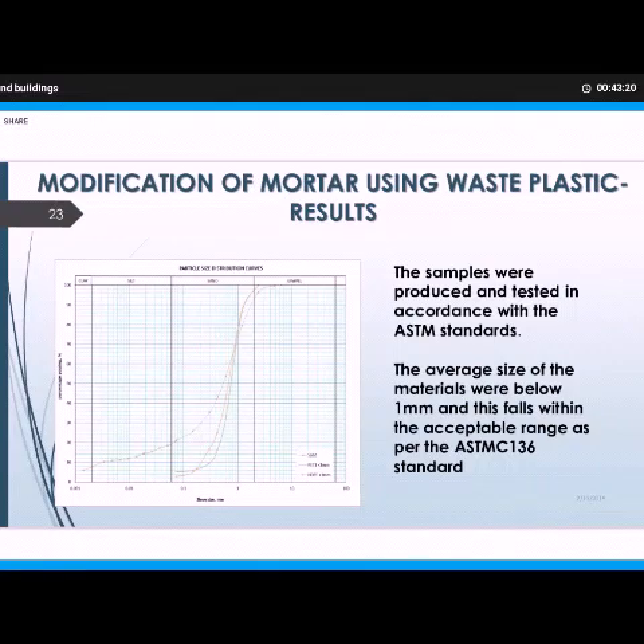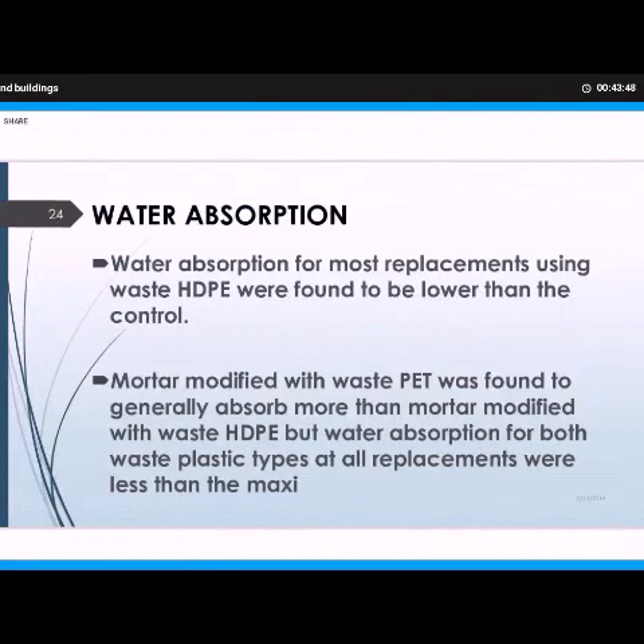Modification of mortar using waste plastic. The samples were produced in accordance with the ASTM standard, and the average size of the materials was found to be below 1 millimeter, and this falls within the acceptable range as per the ASTM C136 standard. The water absorption for most of the replacements using waste HDPE was found to be lower than that of the control. Mortar modified with waste PET was also found to generally absorb more than mortar modified with waste HDPE. However, the absorption of both plastic types and for all the replacements was far less than that of the control.